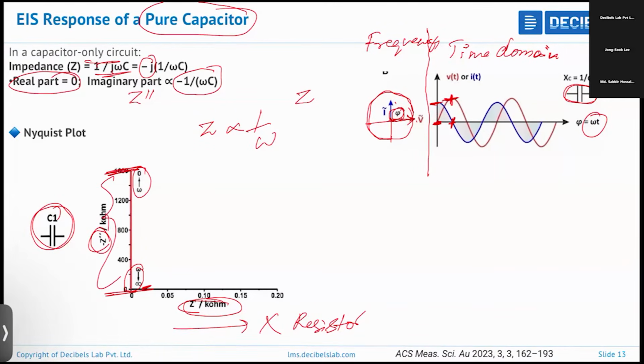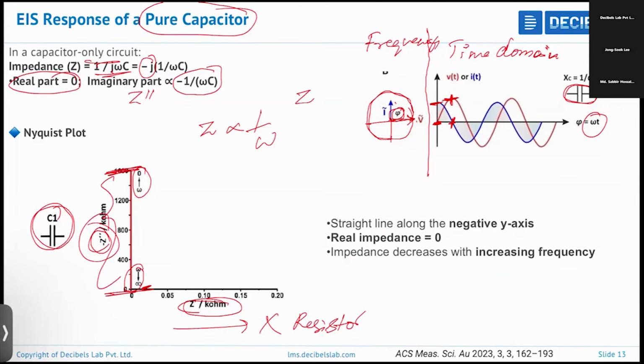This is the impedance. So it's inversely proportional and parallel to the y-axis. Parallel to the x-axis is the resistive. Parallel to the negative Z imaginary is a capacitor. On the straight line along the negative y-axis, the real impedance is 0. That is a takeaway: impedance decreases with increase in the frequency.